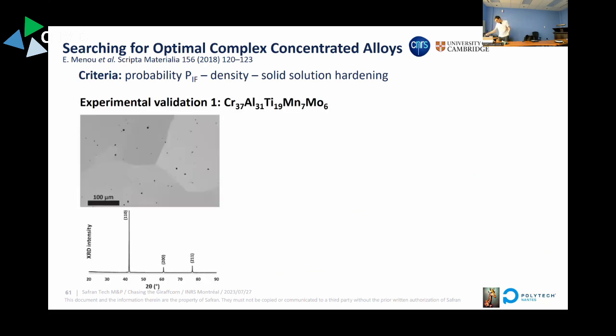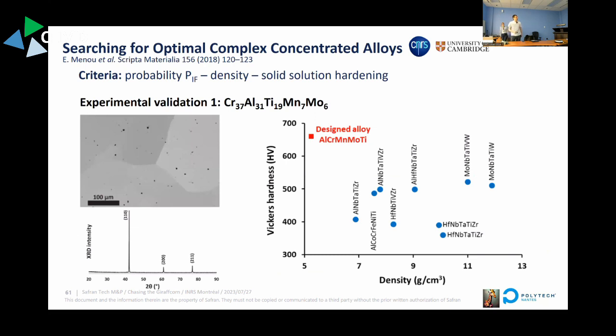And so we entered that in the genetic algorithm, and had 7 alloys made, 2 of which I'm going to concentrate on. The first one is a BCC alloy, validated as having a very stable microstructure with very large grains, a single phase microstructure as well. And this alloy was very interesting because it featured a specific hardness which is very, very high for its category of alloy. So this alloy has basically no ductility at all. It's not of any use for structural material, but as a curiosity, it's very interesting.